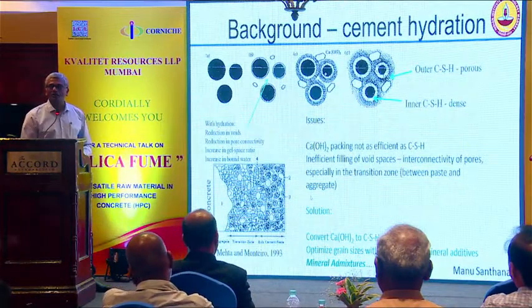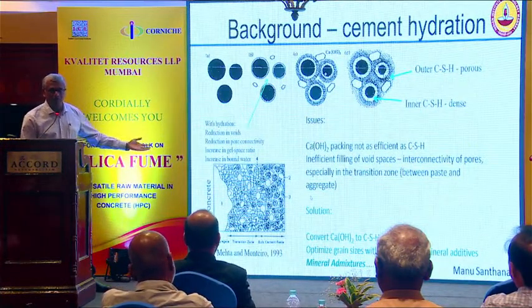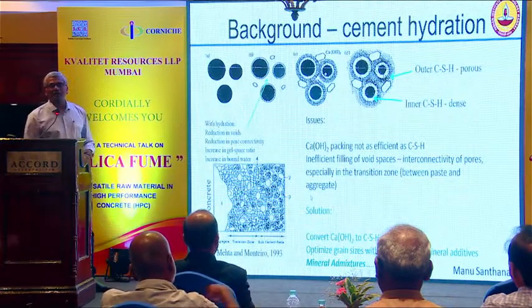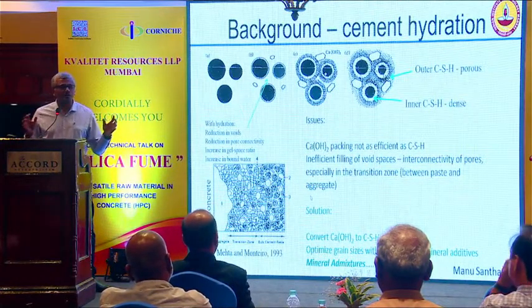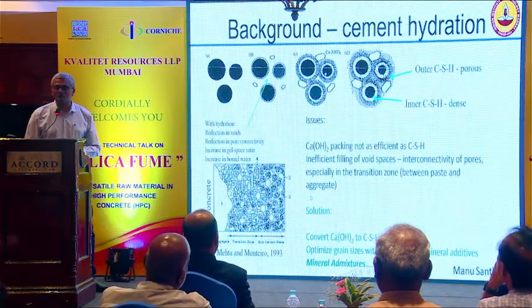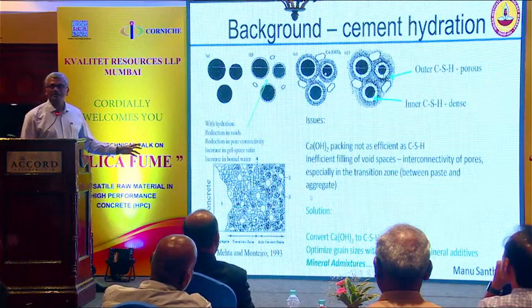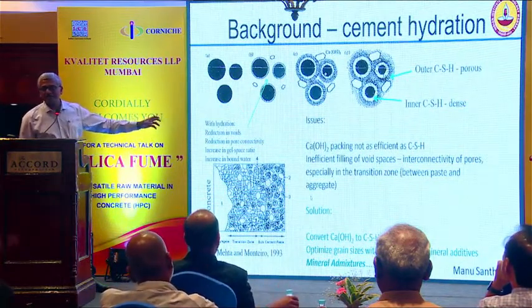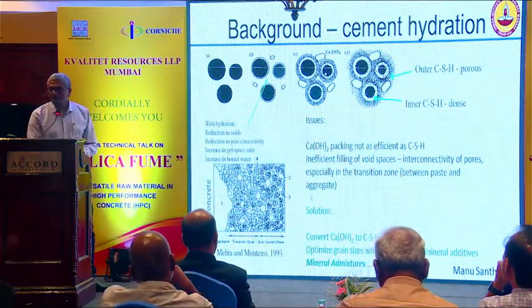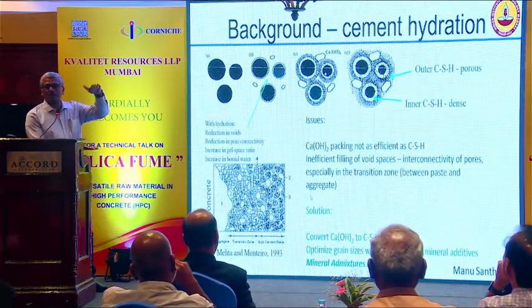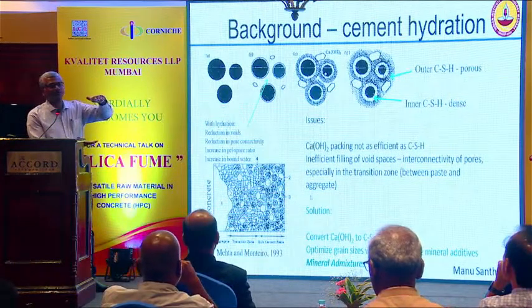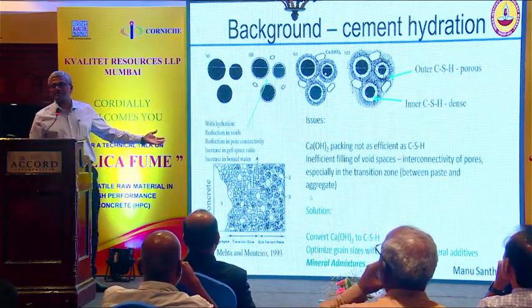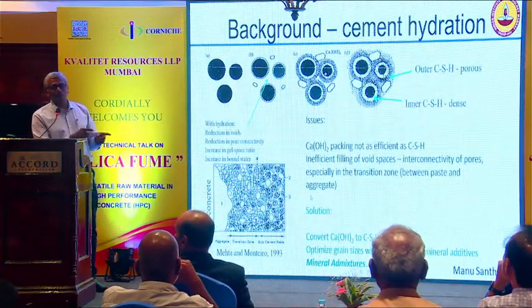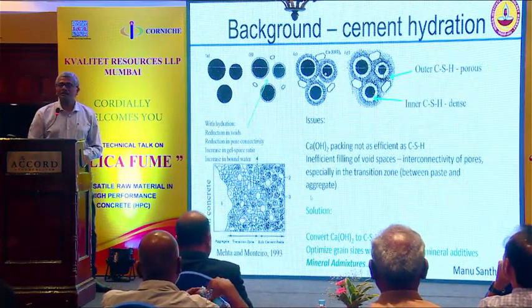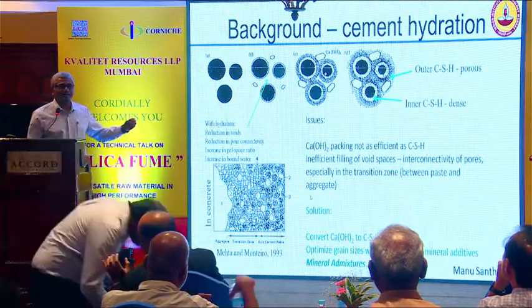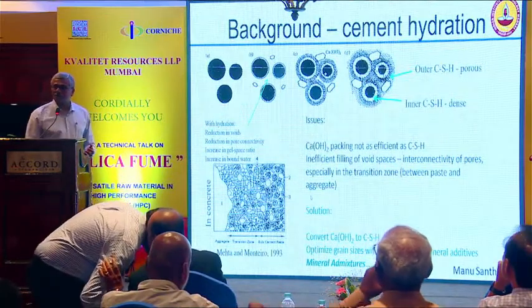So generally in concrete, if you notice near the aggregate, there'll be more porosity, there'll be more calcium hydroxide, and there won't be as much calcium silicate hydrate, which is the primary binding material that is formed when cement reacts with water. So as a result, we have a situation where there is an inefficient packing near the aggregate. So whenever there's loading of this concrete, the load obviously will concentrate around the stiffer regions. Aggregate being stiffer than the paste will take more load, and the zone around the aggregate will have a slightly higher extent of stress, because of which cracking in the interfacial transition zone begins without much loading itself.